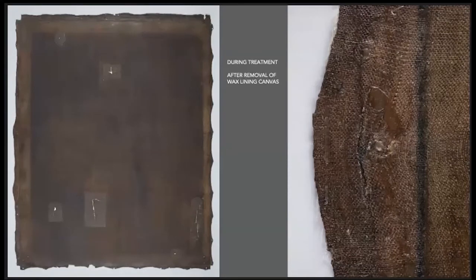It was difficult to remove all of the residues from the wax resin lining. They could be removed through aromatic solvents, but not completely. And in some cases, it remained impregnated in the interstices of the canvas weave, but reduced to allow for an even relining process and good adhesion between the new lining canvases, which we would attach. The ability to view the reverse of the canvases after delining allowed us to observe previous restoration campaigns. On the left, we see residues in the shape of rectangles and squares around old tears that had been previously repaired. Prior to the old wax lining, these tears were once supported with patches made of canvas and other similar materials.